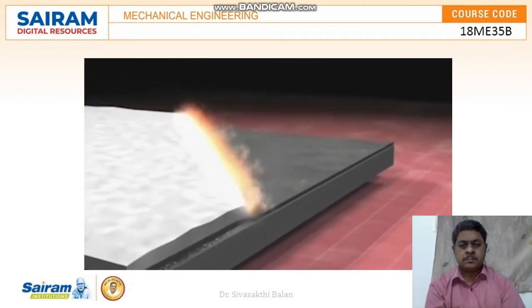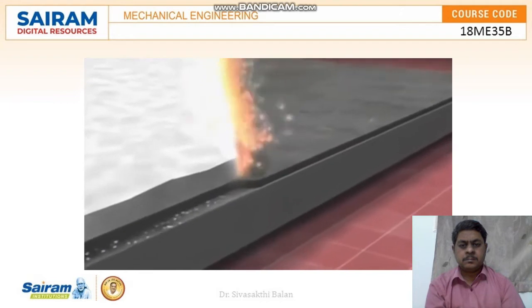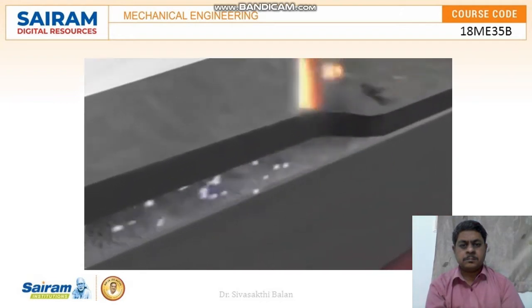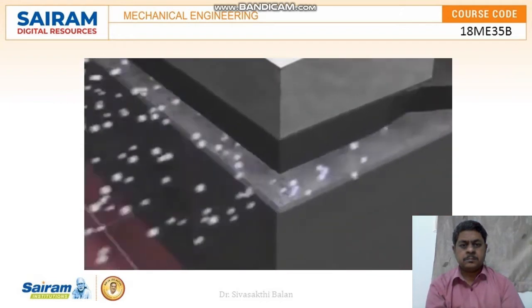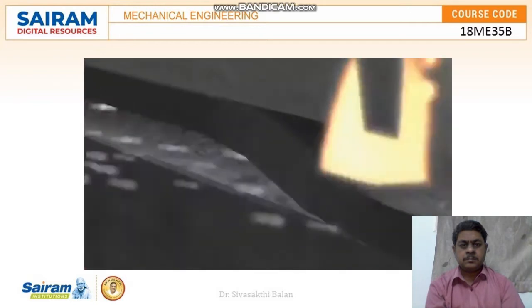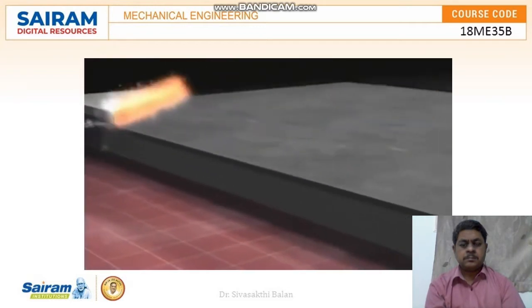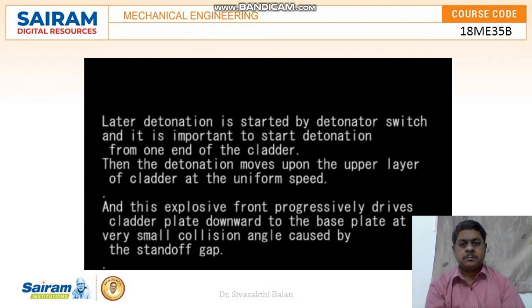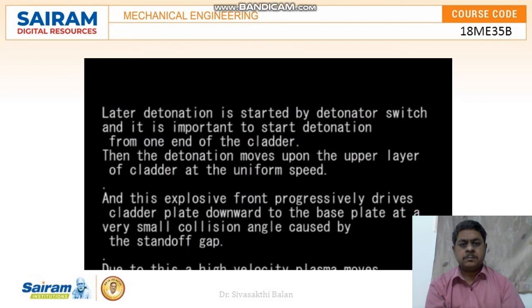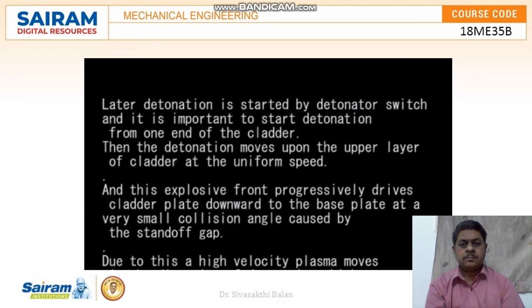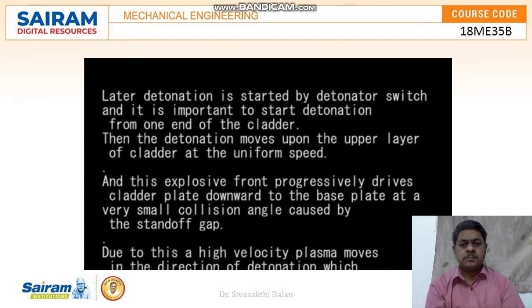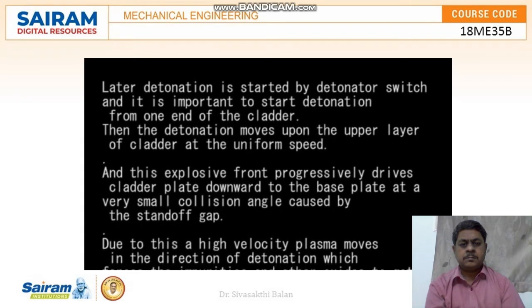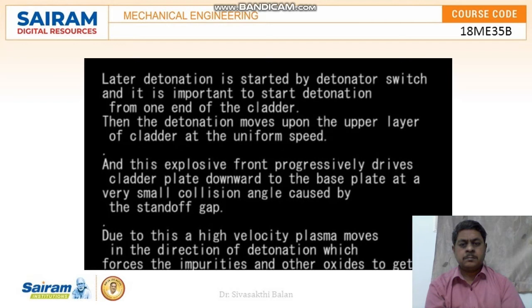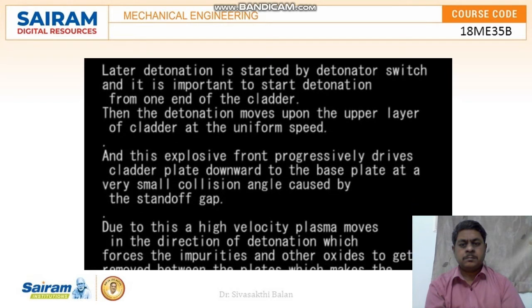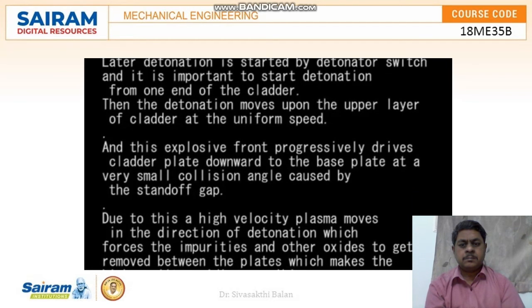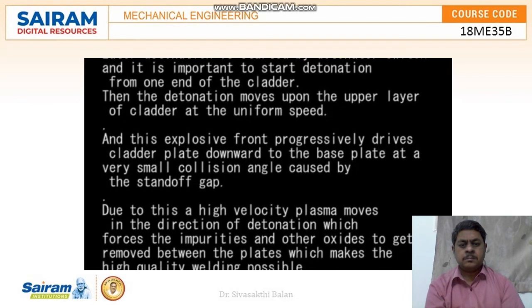And right above it, we put some explosive uniformly. It is utterly important to decide and calculate the quantity of explosives and the velocity of explosion. Later, detonation is started using a detonator switch, and it is also important to start detonation from one end of the cladder. Then the detonation moves along the upper layer of the cladder at uniform speed, and this explosive front progressively drives the cladder plate downward to the base plate at a very small collision angle caused by the standoff gap.